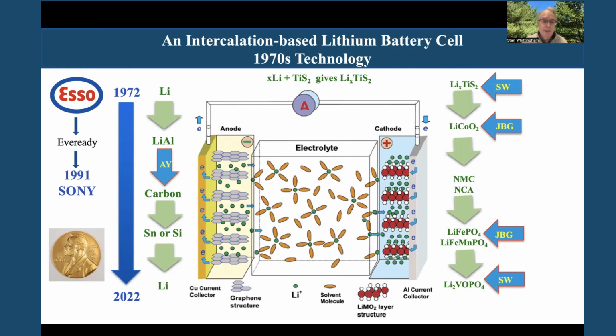But the challenge here, you need 72 grams of carbon to store 7 grams of lithium, and the carbon takes up half the volume of the cell. So the carbon has to go if we're going to increase the energy density. So people are looking now at replacing the carbon with tin or silicon. Tin or silicon both react with more than 4 lithium ions. So their capacity is the same basically as lithium metal. But our goal eventually is to get back to lithium metal.